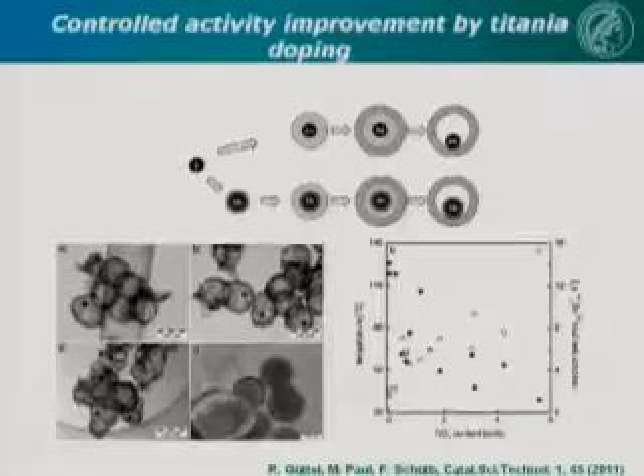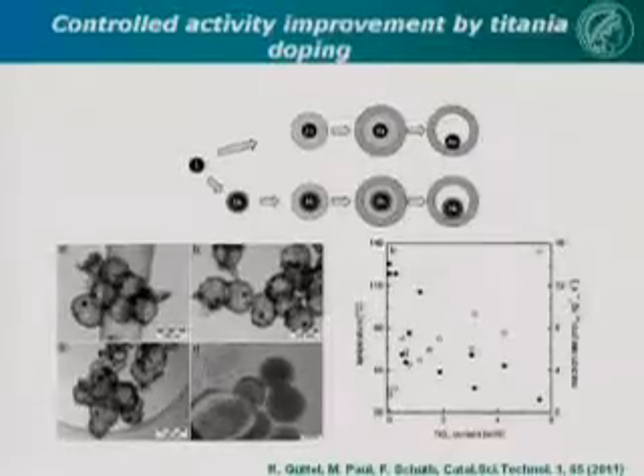You can also do other things, also fundamental studies of these gold catalysts. You can dope with titania, which is supposed to be an activator for CO oxidation catalysts, gold-based CO oxidation catalysts. So we coat, for instance, in this case with a little bit of titania, then we coat with silica, then we coat with zirconia, then we leach the silica, and then we have a gold particle decorated with titania in a zirconia shell.